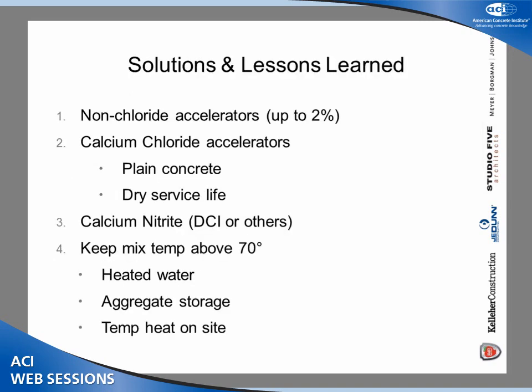What we found is that non-chloride accelerators are helpful, up to 2%. I will allow calcium chloride accelerators in plain concrete that has a dry service life. That's even more effective. A known accelerator that we use in parking decks, pool decks, bridge decks is calcium nitrite. It is a known accelerator and corrosion inhibitor, so you get a double benefit. It's not cheap, but keep that in mind for your extreme condition concrete, your corrosive environments.